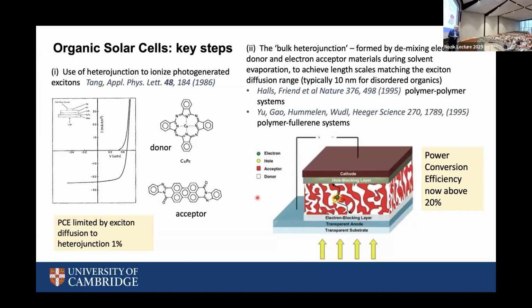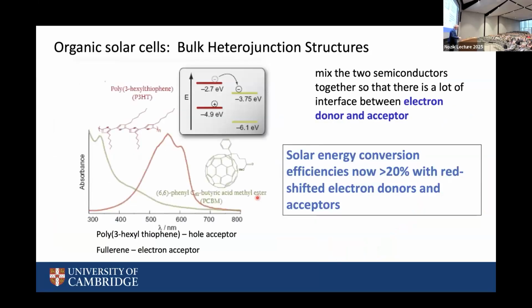And essentially, you can get close to 100% charge collection with that structure. So that happened in 1995, and since then there's been a huge effort to make organic solar cells work. This is an early, just where I say a bit more about that process of charge transfer. On the left, we have the valence and conduction levels for a donor, it's a polymer in red, and then offset levels for an acceptor, which happens to be a derivative of fullerene.